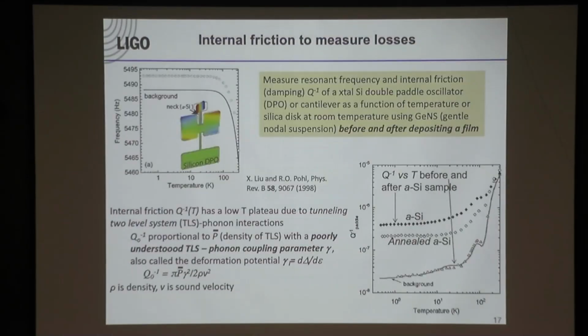Okay, so with that, I already mentioned that the way we measure this is we have these beautiful double paddle oscillators. They're single crystal, they have incredibly high Q. They measure a pure shear mode, which is convenient, so we know exactly what mode we're exciting. You put the film on and you measure the Q. There's the pure DPO, and there is the one with the sample on it. It's not literally a subtraction, but that's the idea. And out of that you get the film.